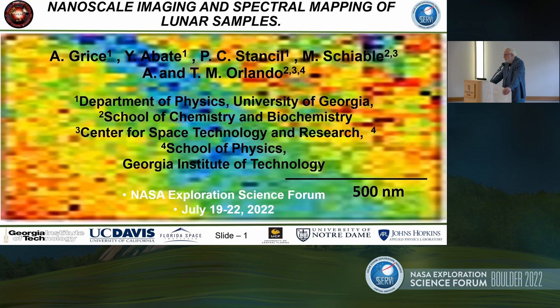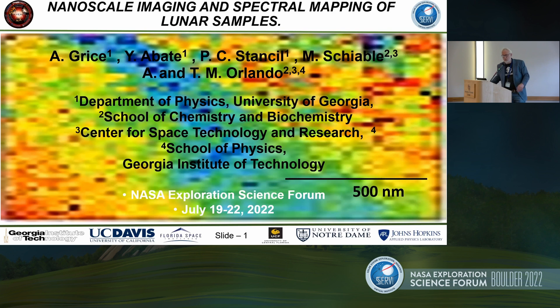I want to point out the title slide — there's actually useful information on it beyond the pretty colors. It's a hyperspectral map of a lunar sample. The scale bar on the right is 500 nanometers, and if you look at the delineation zones between the red, blue, and green, the pixel size is on the order of 10 nanometers. We're doing spectroscopic mapping of surfaces at the 10 nanometer scale while obtaining real topographical and spectral information simultaneously.